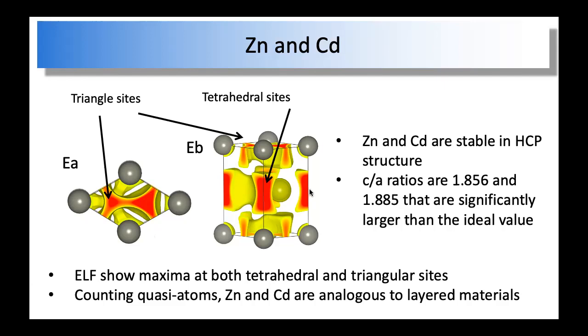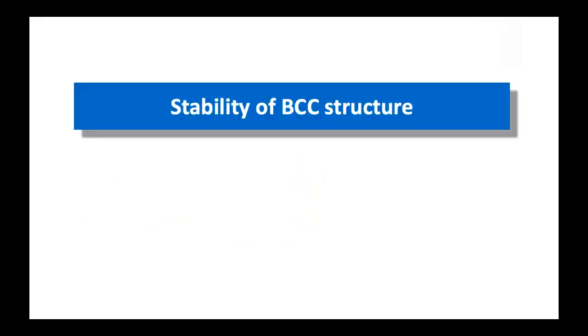In total, they have very strong interactions there, but very weak interaction between the different stacking layers. So if you view this as a compound, it actually is a layered compound. Okay, so it forms a layered structure. The interaction between the layers is pretty weak. Therefore, the c/a ratio is exceedingly large. It's very, very large. Okay, so this is the story of the HCP, the close packed structures.